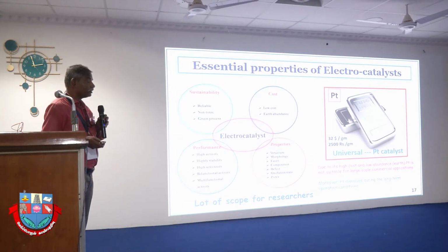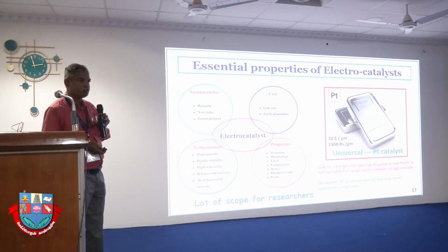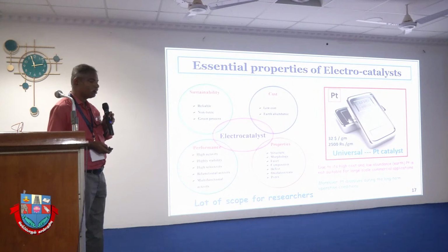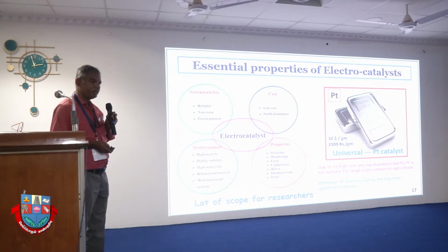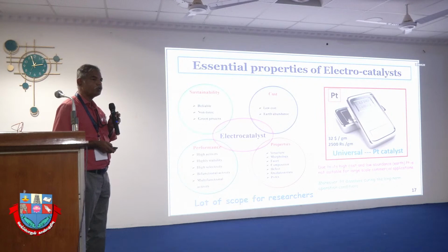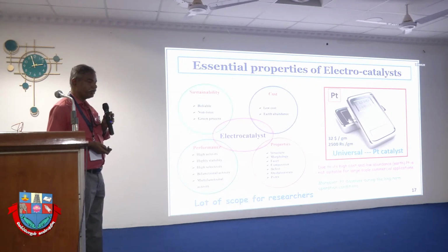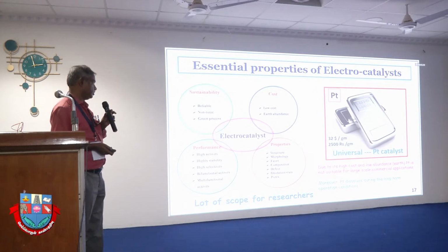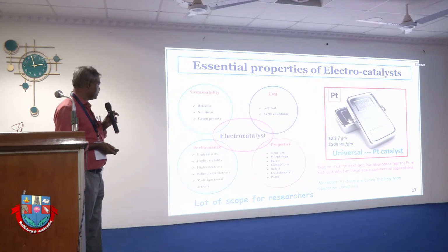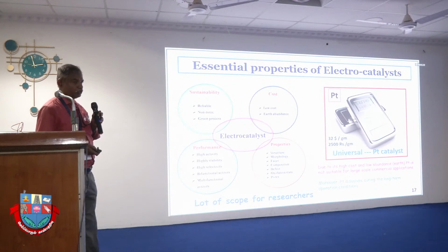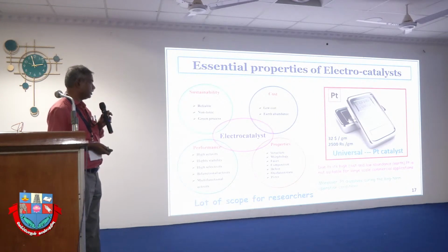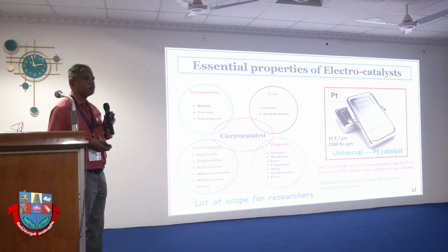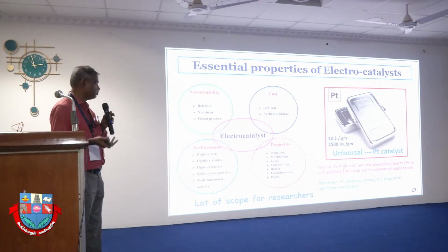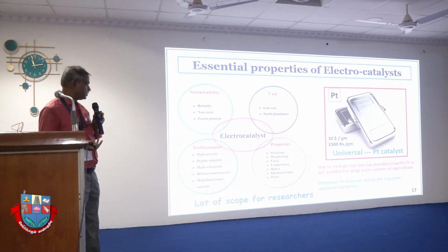So people are now actively looking for a replacement to do the job of platinum, but it's not easy because it's a God-given gift. Platinum will take care of both HER and OER, but if you want to go for a non-platinum based material, it is very, very difficult, because we need to look at many things. Cost is one thing. The other thing is performance, which should be very active. It should be a low overpotential material, and property-wise there are many things that need to be tuned, such as surface morphology, porosity, and crystal phases.